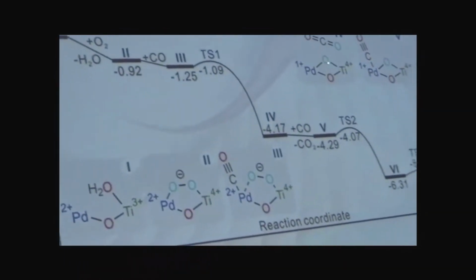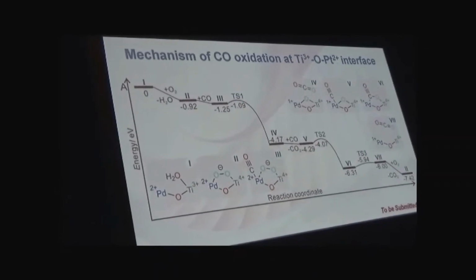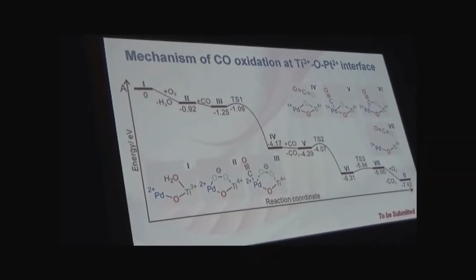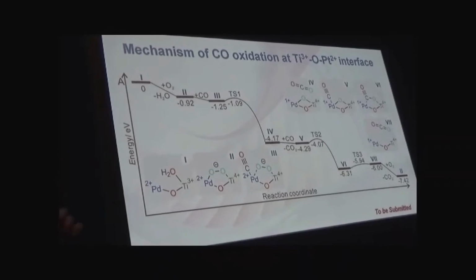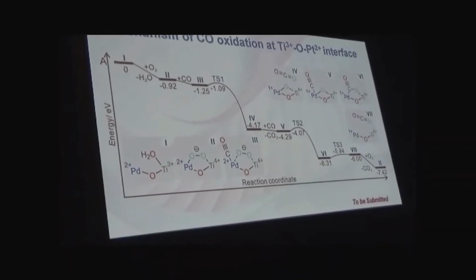Here is the mechanism. Here the oxide and CO adsorption, and CO can react with the oxide with a very low barrier, and then CO can react with the oxygen. Here also is a very low barrier, and then the final CO2 desorption. Here's the full mechanism. So in this case, it's a single atom system with two active sites. One is the palladium, the other one is the titanium 3+. So it's a single atom, two active site system.